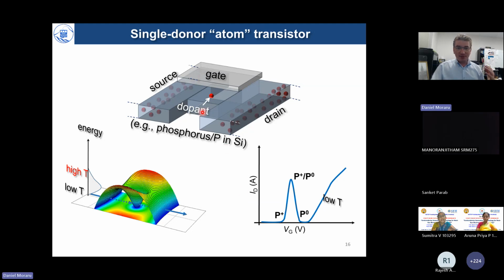Okay, so of course, but this can be perceived as a positive effect. So if you reduce less than 10 nanometers quantum confinement, and if your device is embedded in an insulator, dielectric confinement will also play a key role. So if you do that, the dopant states will become deepened and probably randomly deepened, and we cannot treat the dopants as classical textbook dopants anymore. And of course, the surface effects, interface effects will be very important. So annealing can be one solution, or very precise control of dopants with some sophisticated techniques can be another one. STM manipulation is demonstrated in Australia, by the way, and we can hope for that kind of more practical application. Yes, sir. Thank you, sir.